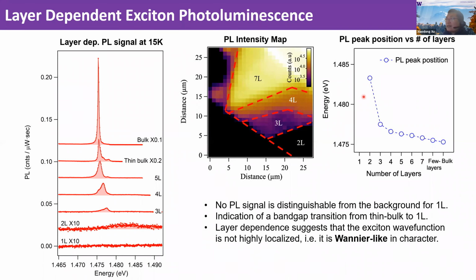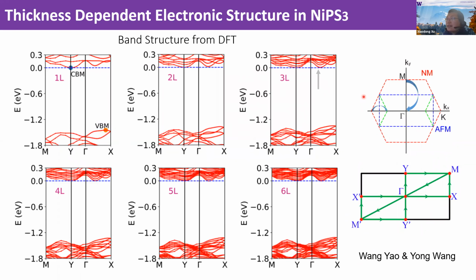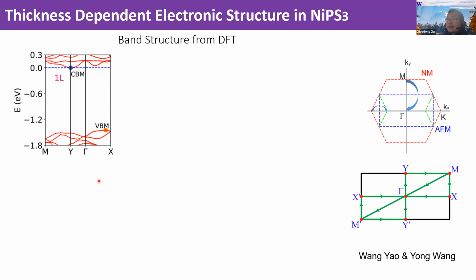Now we look at the calculations, right? The calculation basically shows two things. The first is that when I increase the layer thickness, this peak in this band edge actually lowers down. I understand that, but what I'm confused about is that your magnetism does not play any role in this. No, magnetism doesn't play a role here. This is just a simple band structure. Yeah, but your exciton actually couples to phonons and probably some magnetism. So why is the magnetism completely decoupled in this PL intensity? Actually, I don't know why it's decoupled.